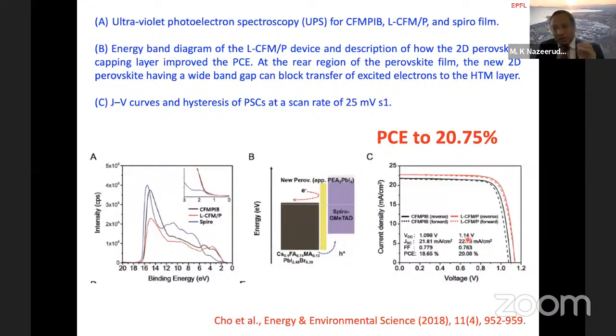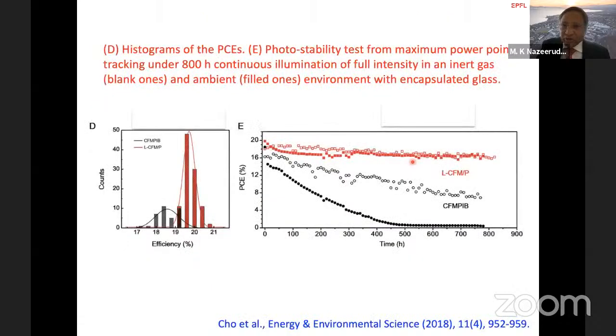So even though this number looks too small to you, this is a significant number for us to tell that the recombination has significantly reduced. So the optimized efficiency is close to 21% using this three-dimensional perovskite and two-dimensional perovskite.